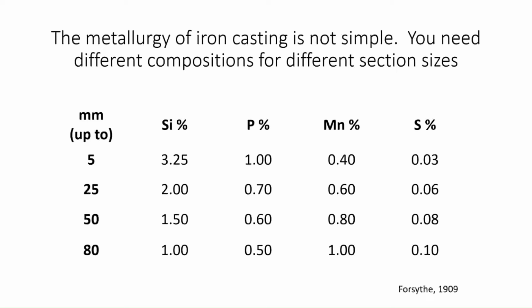So why? Well, there are two phenomena involved here in this particular science, if you like. First of all, with the very thin castings, you had to be careful to get the right kind of iron in the first place, because out of an 18th century blast furnace, you could get two completely different kinds of iron. It all depends on how that 4% of carbon in the cast iron precipitated into the solid structure. If it precipitated as iron carbide, Fe3C, then it was known as a white iron. If it precipitated as graphite, then it was known as grey iron.